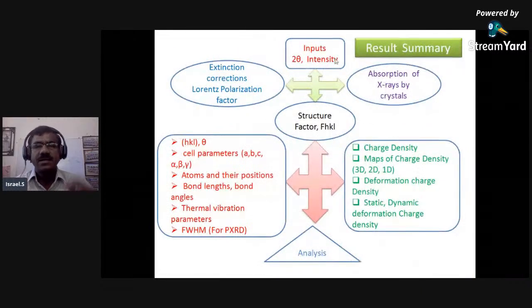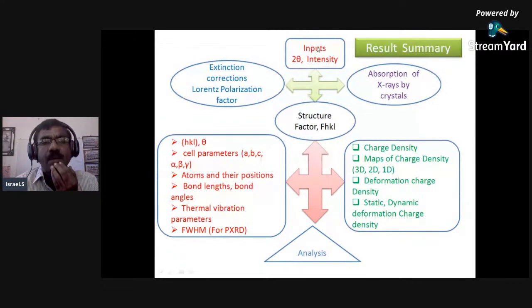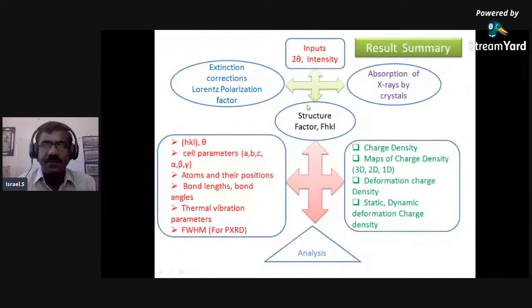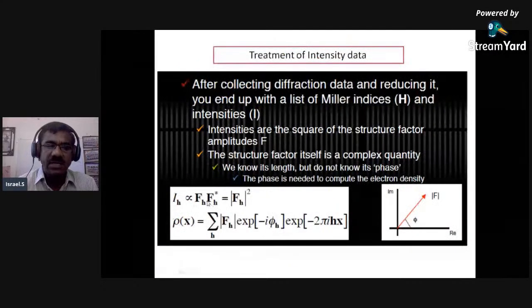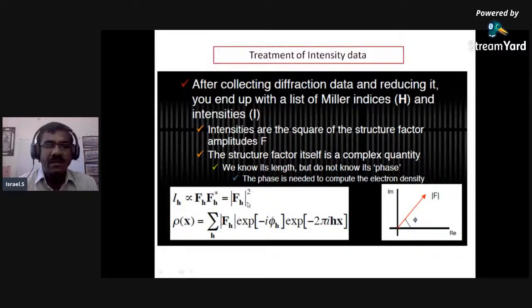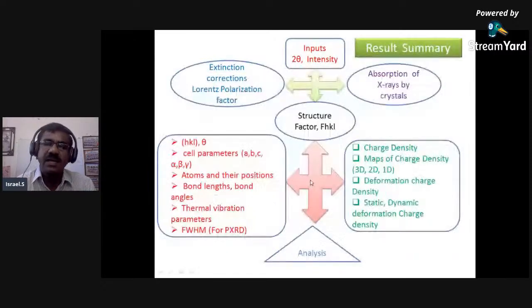And this is the result summary. From 2 theta and intensity from the X-ray diffraction experiment, you convert that intensity into a structure factor, which is nothing but the square root of the intensity. The intensity is the structure factor squared, so you take the square root to get the structure factor. Once you get the structure factor, you can transform it using Fourier transform techniques and convert it into charge density. So from 2 theta and intensity you get the structure factor, and from the structure refinement, these are the parameters that you will get.